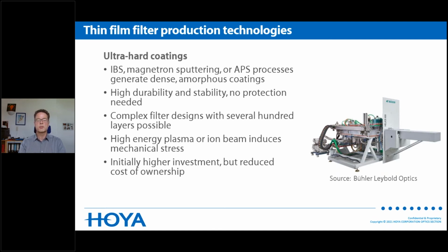The high energy plasma or ion beam induces mechanical stress in the coating, which leads to bending of the substrates. And the thinner the substrate becomes, the more severe the bending is. Another thing to consider is that although these filters have a higher cost, so for the customer an initially higher investment, you still might see that the cost of ownership is reduced because these filters last longer and do not lead to any degradation over time and a bad customer experience.